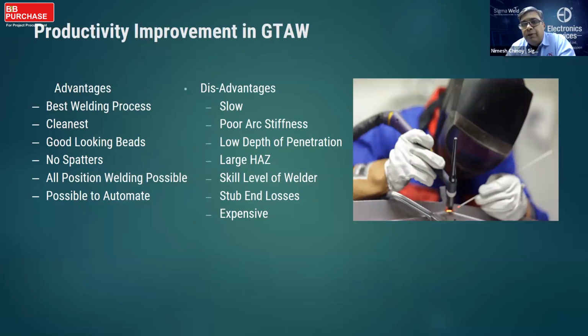However, we always talk about TIG welding being slow, lacking arc stiffness, also low depth of penetration, increased heat affected zone. You need a very skilled operator, and you have stub-end losses, that is 10% of your consumable is thrown away because the operator cannot feed it in time. And therefore, the process is deemed to be expensive.